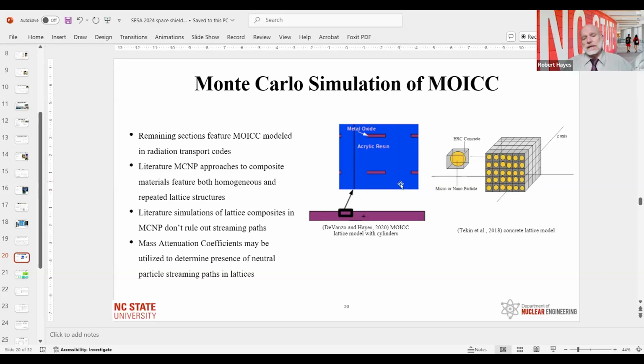And that's attributed to the fact that the resin here, the polymer, has very low attenuation properties. And so these high Z metal oxide particulate, they basically just cast a shadow. When I stack these up, there'll be a bunch of attenuation there, but there's really no attenuation through these sides. You basically have radiation streaming through the sides because you choose to model it as a crystal lattice instead of amorphous material, where if it's amorphous, you're going to get some particulate in almost any path that you go, giving you equivalent radiation attenuation through any path, and that it doesn't average out. And that's what this result found.